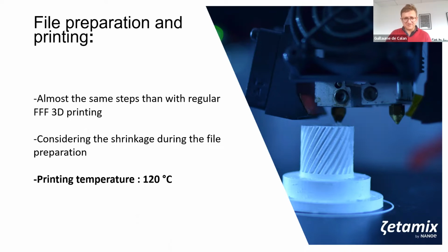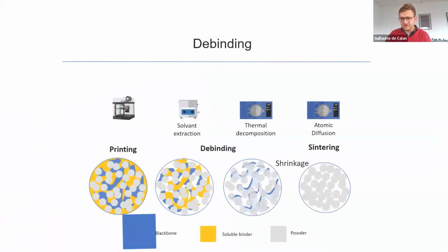So once we have done the file preparation, we have generated what we call G-code, which is lines of instruction for the printer. We will just print on any FFF printer, and then you debind. In that case, it's a two-step debinding process. The first step is to dip the part in acetone, which will remove approximately half of the binder. And then you will have a thermal debinding, which occurs in the furnace, and then sintering.